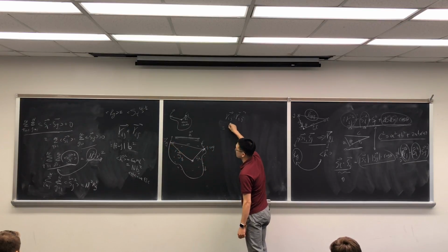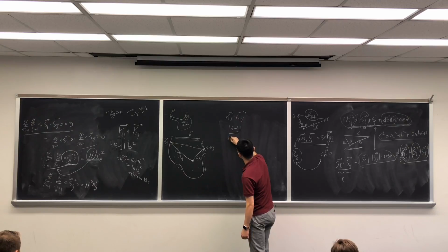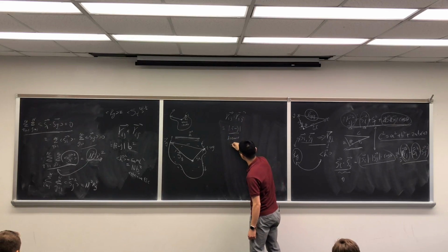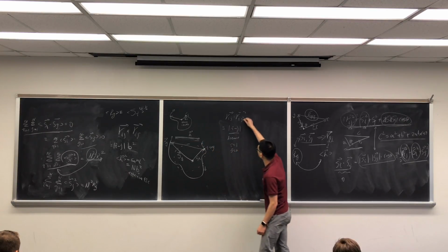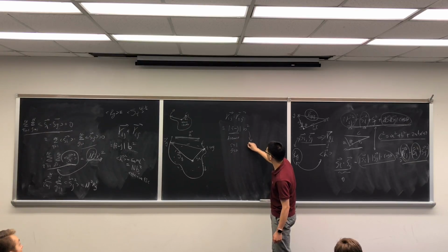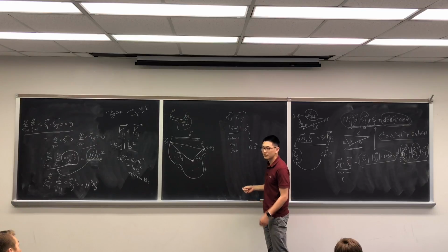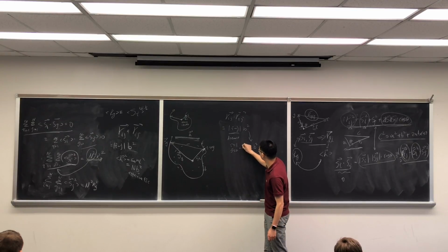It will equal |i minus j| b squared, the distance between each bond, right? If i equals 1 and j equals n, which means this is the first bond and that's the last bond, a special case will be n b squared. That's basically the end-to-end distance.